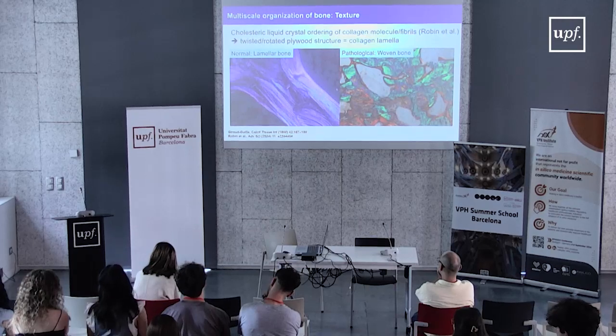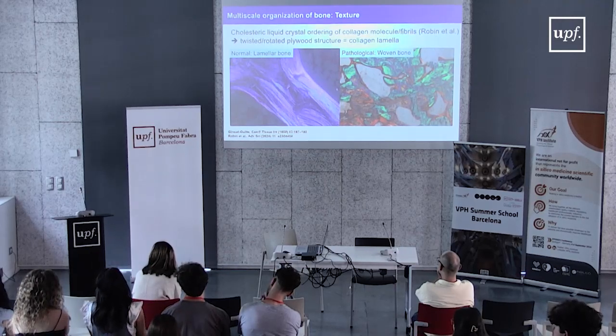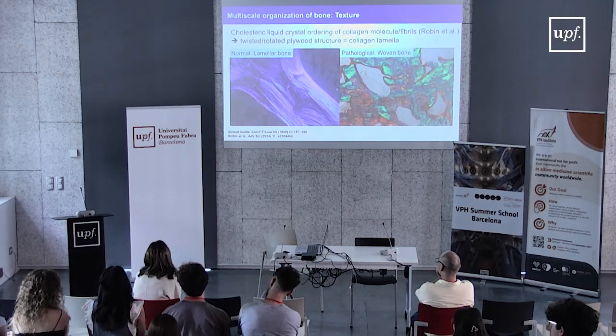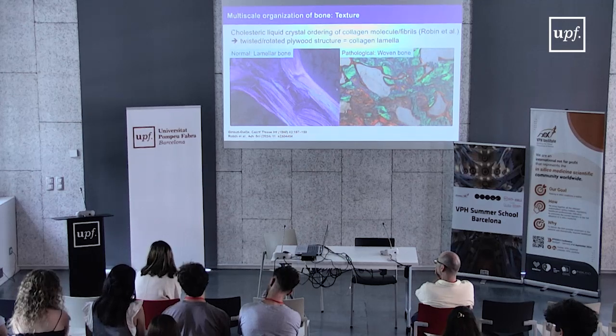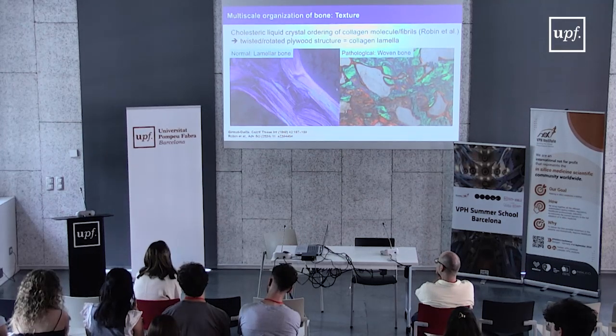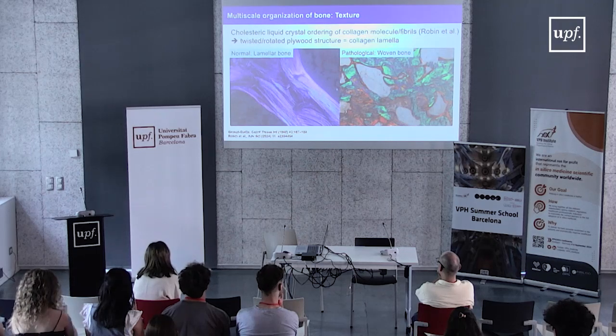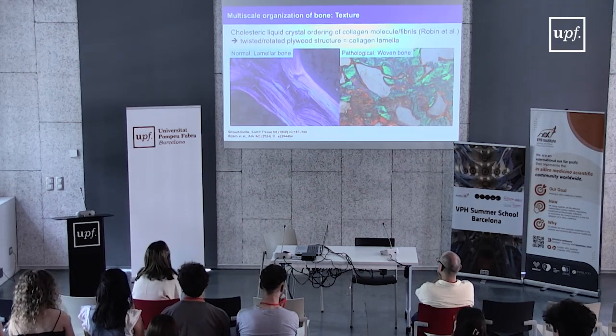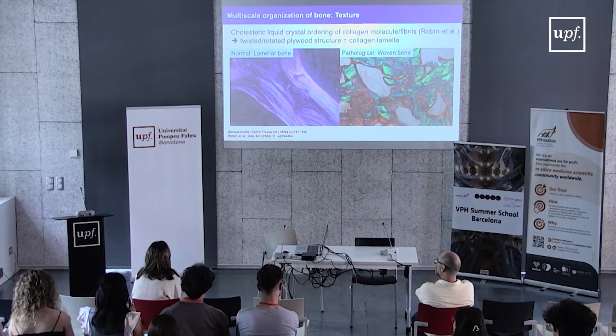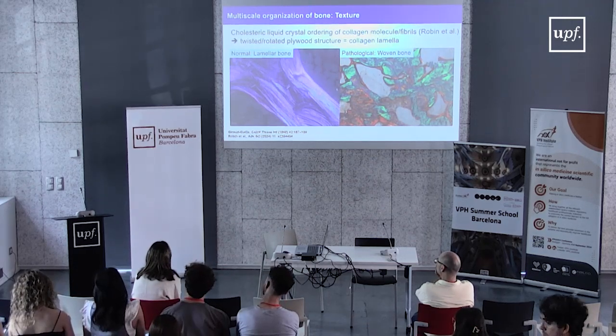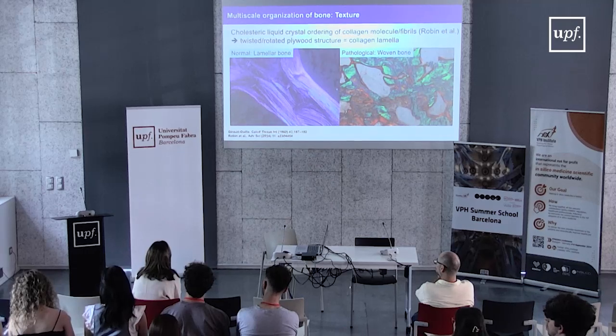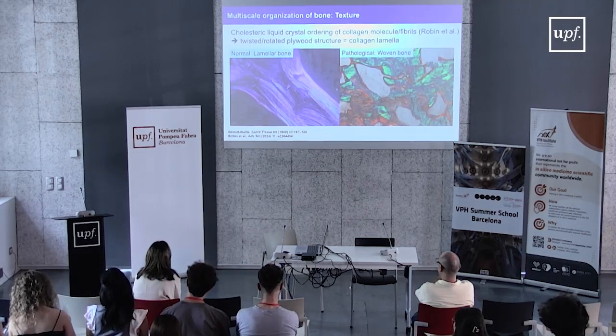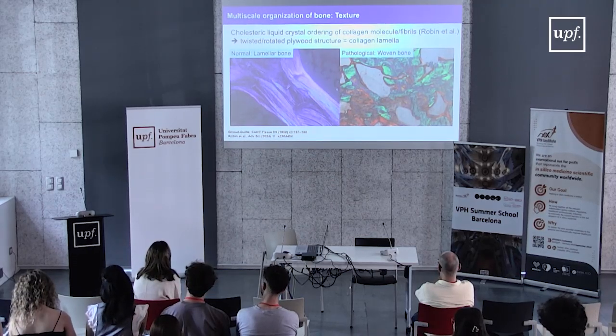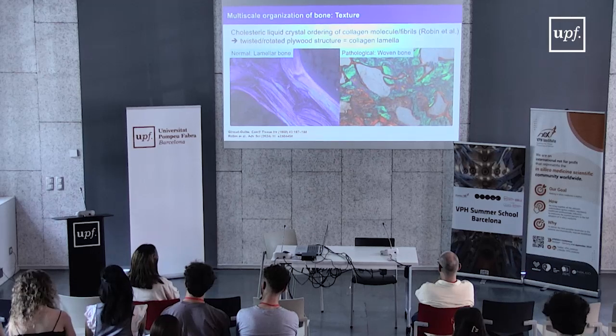If now you have a problem in the deposition of your collagen and the rotation between the different planes, and you don't have a cholesteric liquid crystal form, you will have this type of structure, which is called woven bone. And woven bone is what you will observe in cases where your bone needs to grow very, very fast. So we can see it early in life, and it will remodel into lamellar bone, but we can see it also in pathological disorders like metastasis or Paget's disease of the bone.